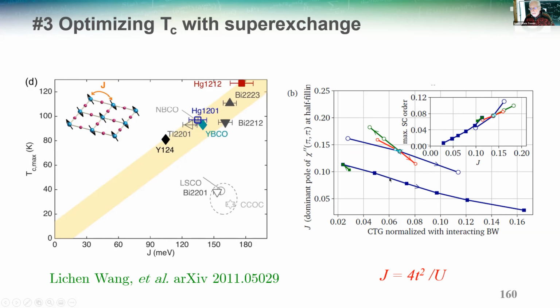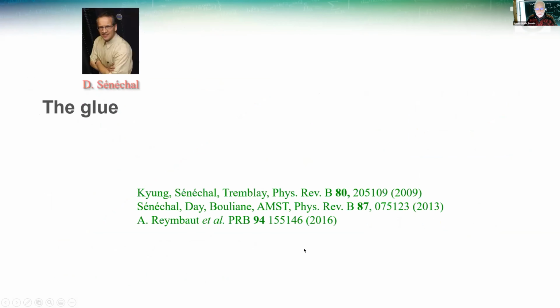And now you can also explain the difference between the covalent and the ionic model, because clearly for the ionic model, the effective hopping between copper is going to be smaller, right? So it's better to be covalent. Finally, let me plot the maximum superconducting order parameter as a function of super exchange. Now you see that both models fall basically along the same line. And that's what these experiments give for TC as a function of J. And there are exceptions that we can discuss. But there's a trend here clearly of relating the maximum TC with J. So we explained that third experiment.